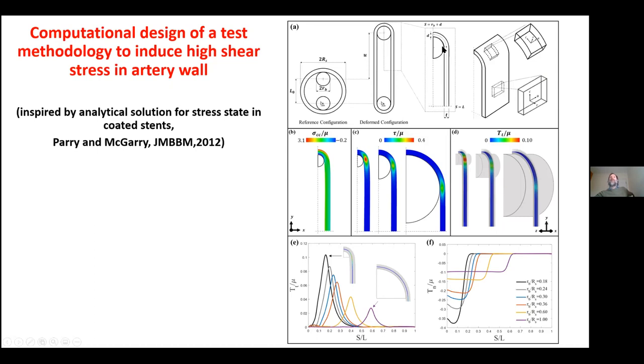And our hypothesis is that in this region up here, where we transition from a circular part to a straight part, we should get a very high shear. So this is what our finite element model is telling us. We should get a very high shear here. And if the material is sufficiently tough to resist radial crack propagation, then we hope that this test should give us a mode 2 crack. In other words, the crack would not grow through the thickness of the artery and cause a fracture, but it would grow between the layers of the artery.